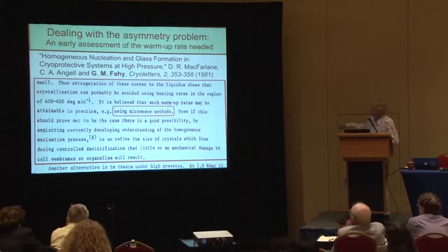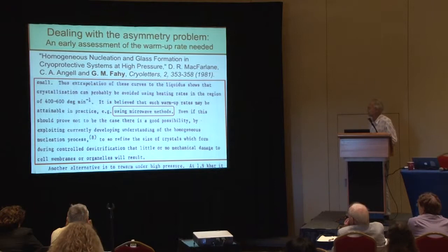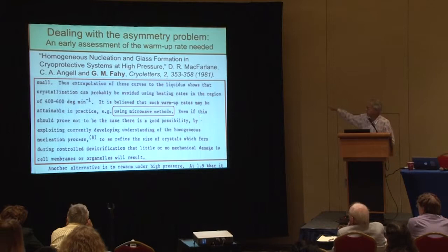let's see. That was telling us that we needed to get the heating rate up, and we speculated about, in this paper with Greg, the first of our papers, about using microwave methods, but of course microwave methods are not going to work for the sort of temperature range which we're interested in here, because we're close to the glass temperature. Microwave is great for water with a relaxation time of picoseconds, but it's no good at all for ice. You can put a block of ice, this surprises many people, into the microwave and turn on the microwave and nothing happens. Not until there's a layer of water around the outside, and then it'll start to melt. But the microwave frequency is totally unsatisfactory for heating ice.